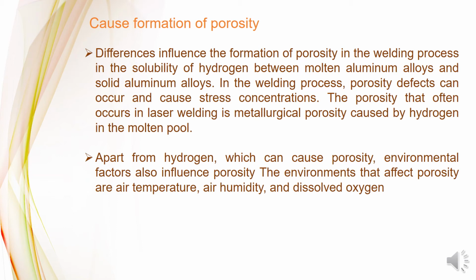Cause formation of porosity. The difference that influences the formation of porosity in the welding process is the solubility of hydrogen between molten aluminum alloys and solid aluminum alloys. In the welding process, porosity defects can occur and cause stress concentration. The porosity that often occurs in laser welding is metallurgical porosity caused by hydrogen in the molten pool.